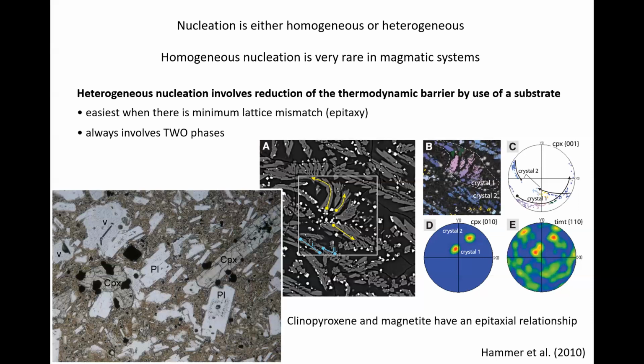And that thermodynamic barrier is reduced even more when there's some kind of lattice matching between the phase that's nucleating and the substrate. And that's generally called epitaxy. And the beautiful example of that, which you will see almost everywhere in mafic rocks, is the epitaxy between clinopyroxene and titanomagnetite. So Julia Hammer's done some absolutely beautiful work on this, and she shows that, yes, there is a crystallographic relationship between those two minerals, and it's very, very easy to nucleate your magnetite on the clinopyroxene substrate, so that's where it prefers to do it.